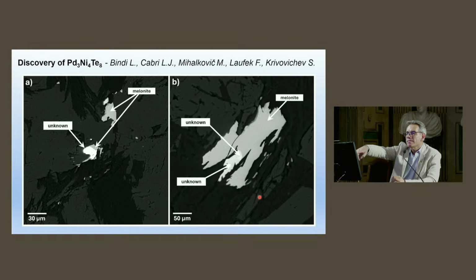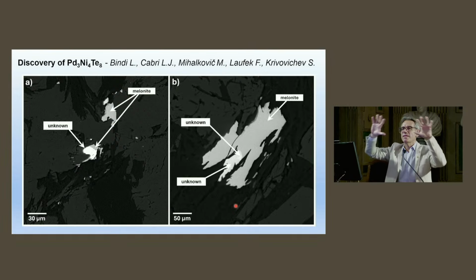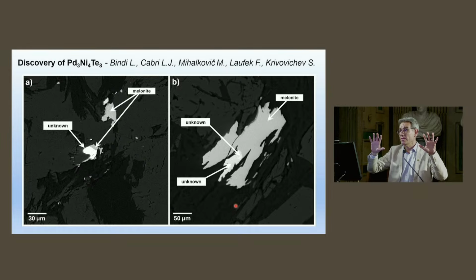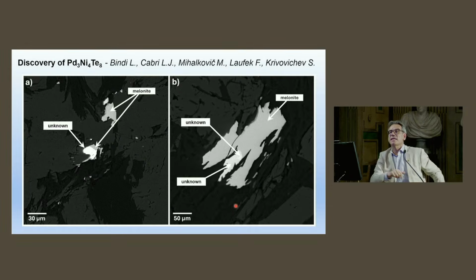Look at these small phases. Look at the bright phase here, which has the composition reported here. It is embedded in another phase called melonite, which is a nickel telluride. All the dark phases surrounding it are silicates, which is the typical association we found in Kalgoorlie.